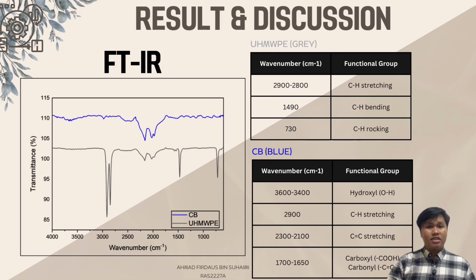The blue spectra is carbon black and the grey spectra is ultra-high molecular weight polyethylene. For ultra-high molecular weight polyethylene, at 2800 is for CH stretching, 1490 is CH bending, and 730 is for CH rocking. For carbon black, at 3600 until 3400 is hydroxyl group, 2900 is CH stretching, 2300 until 2100 is C double C stretching, and 1700 until 1650 is carboxyl and carbonyl.